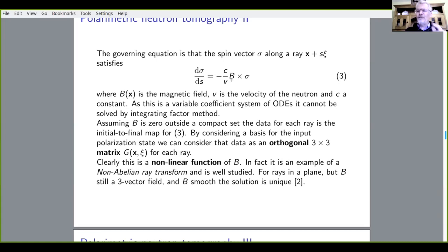this makes it kind of interesting because if you only looked at one ray, you couldn't tell if it had wrapped around once or 100 times by the time it gets out. There is a uniqueness theory that says if you measure from all directions, or actually just all directions in a plane, then there is a unique solution, but it's non-constructive. And in practice, it makes it a difficult nonlinear problem because of what you might think of as a phase wrapping problem.